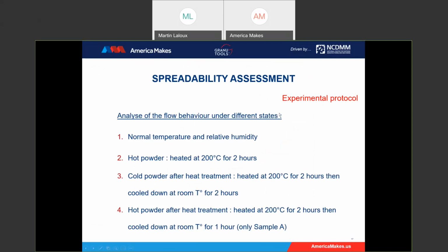The experimental protocol of this study: we analyzed the flow behavior under different states. First, the normal temperature and relative humidity. Then we heated the powder in the drum and measured it at 200 degrees for 2 hours. Then we did the same for the third state: heated at 200 degrees for 2 hours, and then we cooled it for 2 hours. And the fourth state is heated to 200 degrees for 2 hours, and then we cooled the samples down at room temperature for 1 hour. We did that only for sample A.